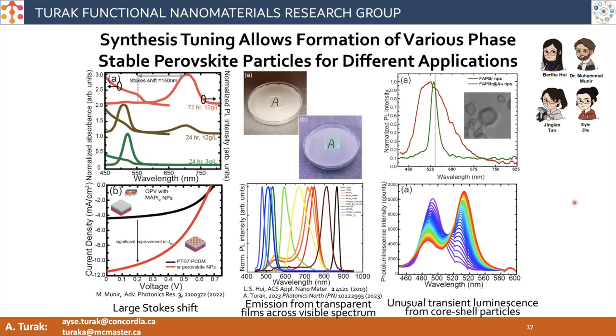And then quite recently, since we started making these core shell structures, so we make a metal oxide shell around a perovskite core. And there we've seen that there's some really interesting transfer interactions between the shell and the core that leads to sort of transient luminescence. So we've seen some really interesting behavior that has not been observed in these perovskite systems before. And since we spent so much time talking about that, I'm going to skip my next two examples.